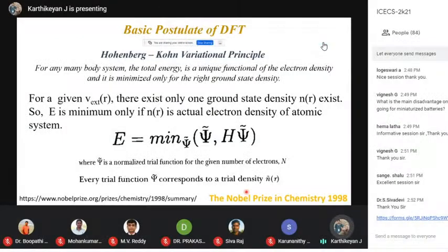From the first trial, we cannot say whether your density is correct or not, but we can change the trial density. When you compare the first and second one, if the energy of the second one is lower than the first one, actually your second density is better than the first one, or we can say the second wave function of the n electron system is better than the first n electron wave function. So in that way, we can keep changing the electron density and approach the minimum of this energy.